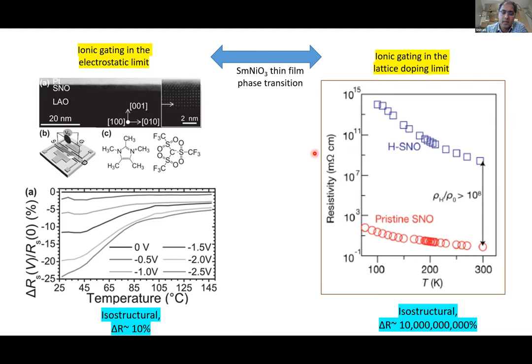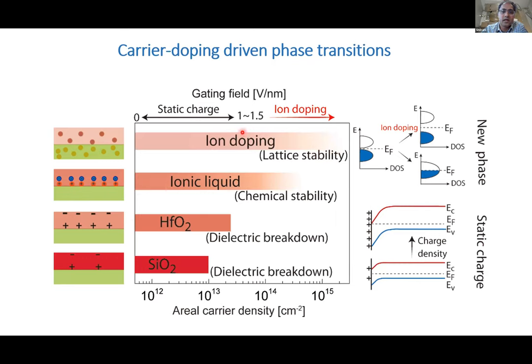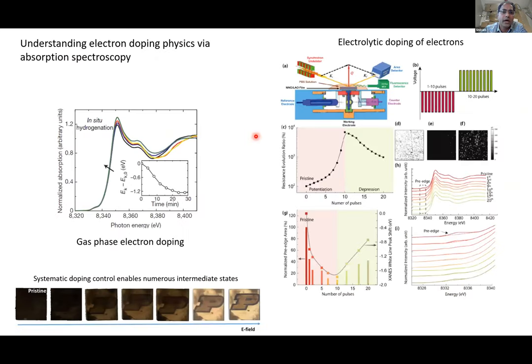So this is really a basic research field. I think this can sustain several decades of research in the future, because if you go back and look at the silicon literature or even hafnium oxide, it's anywhere between 20 to 25 years of research to develop a good gate insulator for a semiconductor, right? These gates don't do anything for correlated semiconductors. You really need gates that can introduce charge carriers roughly 100,000 to a million fold larger than what silicon dioxide and hafnium oxide have done for silicon. And so this is a very interesting, important area of research that deserves a lot of attention in the future.